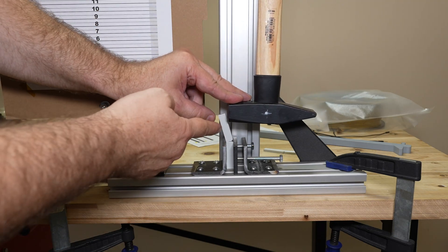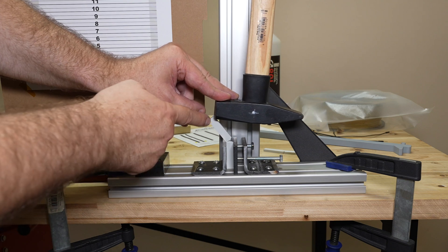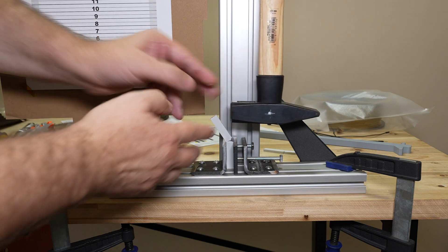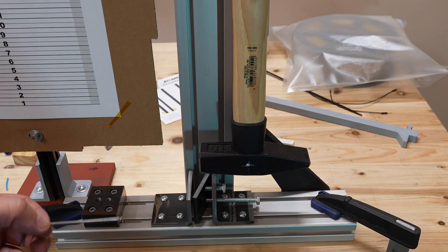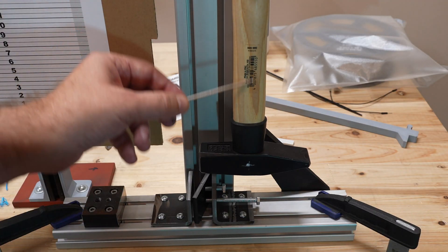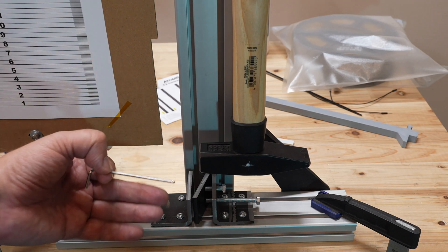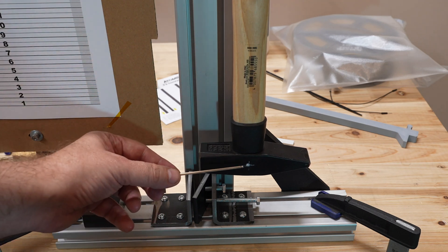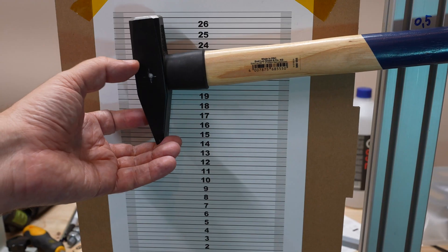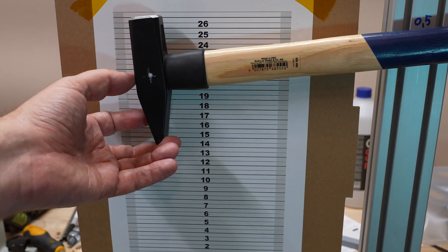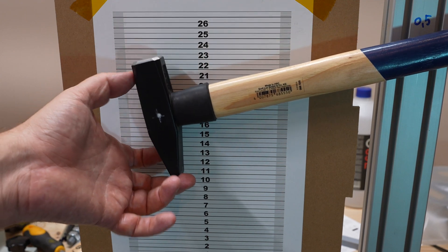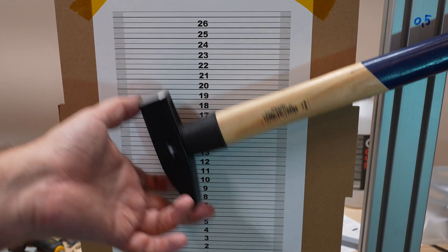If the contact point is somewhere on the top, it will break with a much bigger breaking energy because the brittle filament will break immediately without any bending. The tough filaments on the other side will bend, and it will result in a lot of friction as you can see because of the chamfer. That's why again it will measure much higher breaking energies. Another thing that I neglected is the mass of this wooden part.